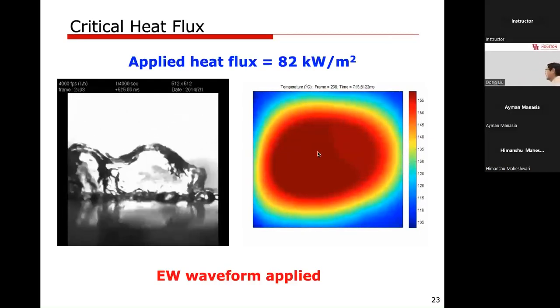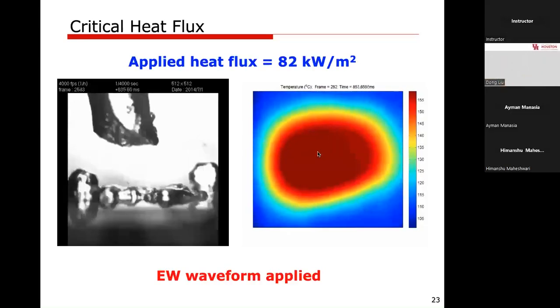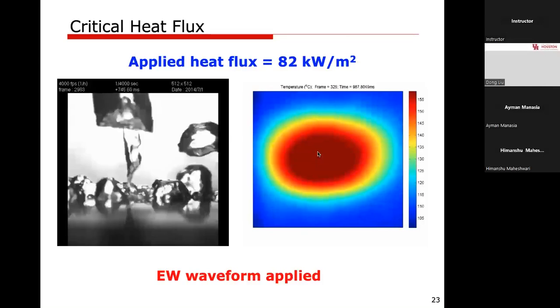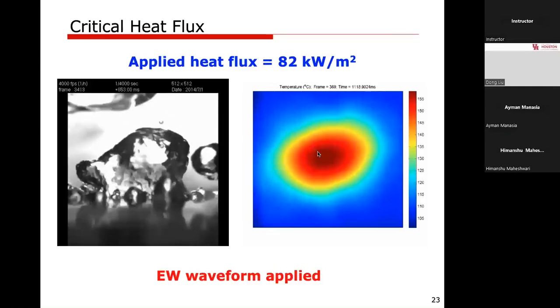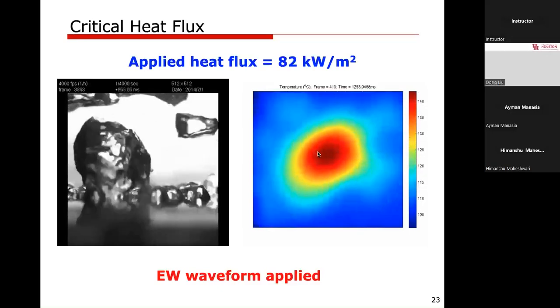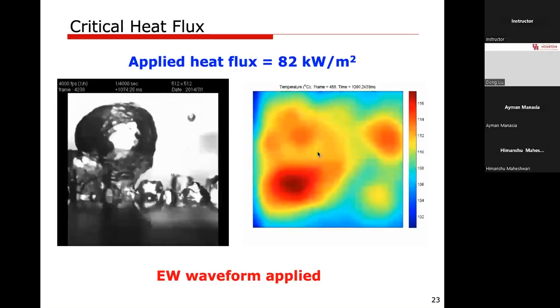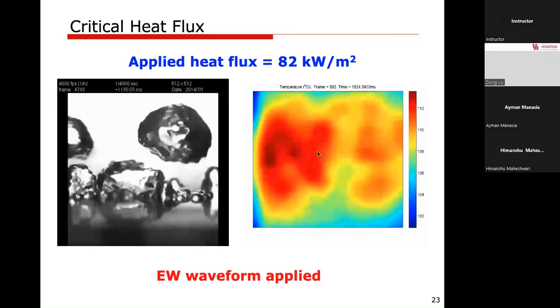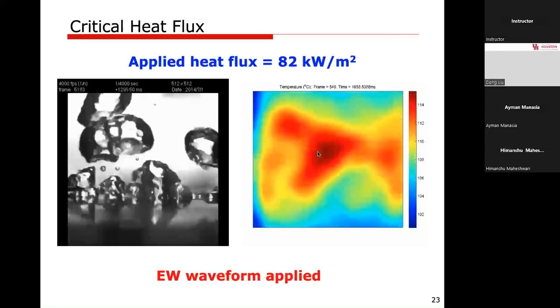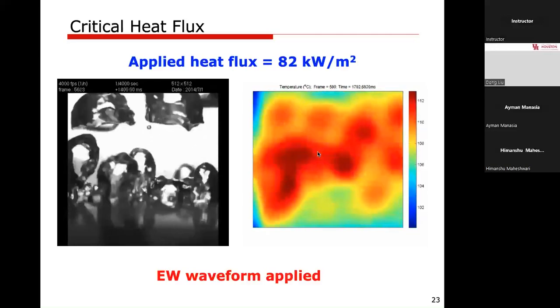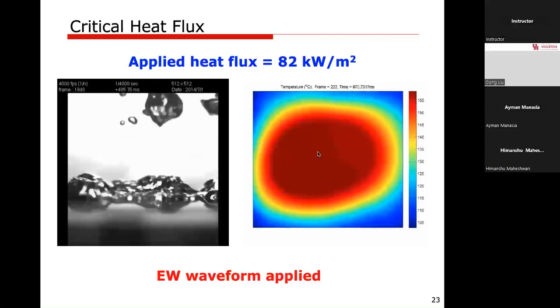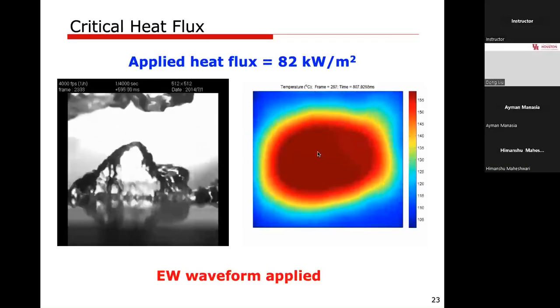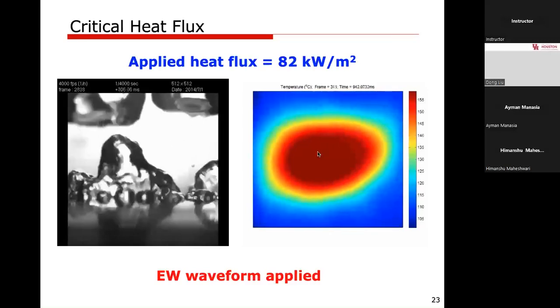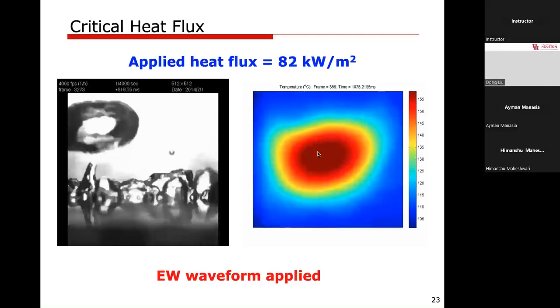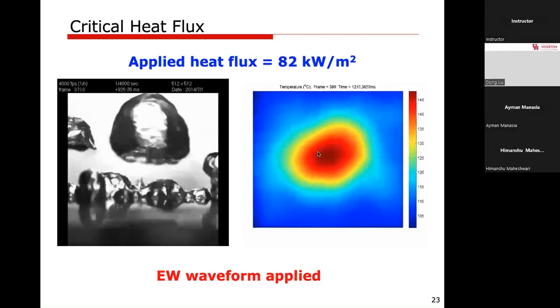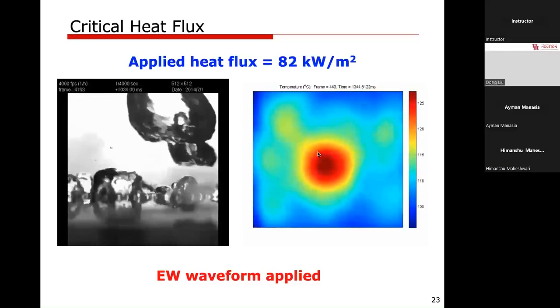So let's see the pictures again. This is the infrared camera. Each pixel is about 25 microns, so the spatial resolution is 25 microns per pixel. Okay, so if you look at this again, this is a film boiling. So the entire surface is covered by film. Maximum temperature very high. Then the vapor film disappears. You see the individual bubbles.